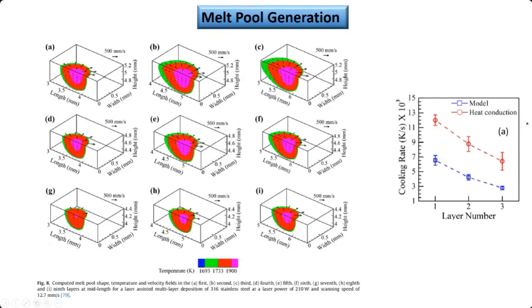So again, if we look at the cooling rate, it is related to the distance of the additively manufactured component from the substrate, near the bottom versus near the top. There is a huge difference between these two levels, and we can see a drastic change in the conduction level and the cooling rate with increasing layer numbers.